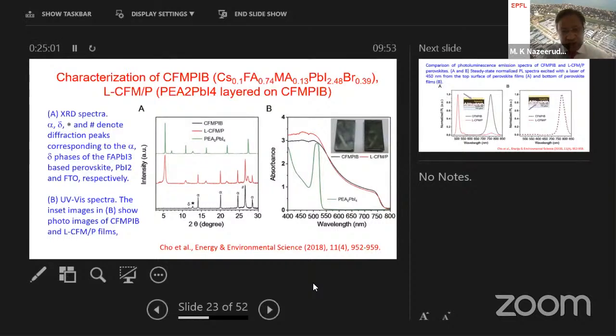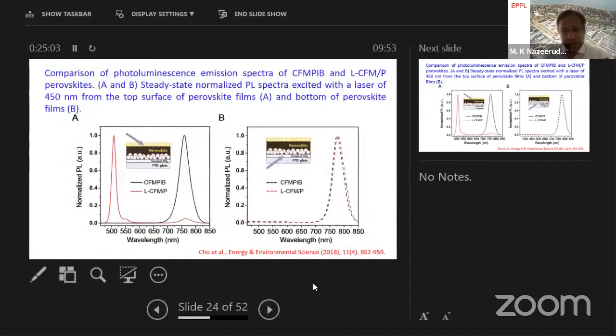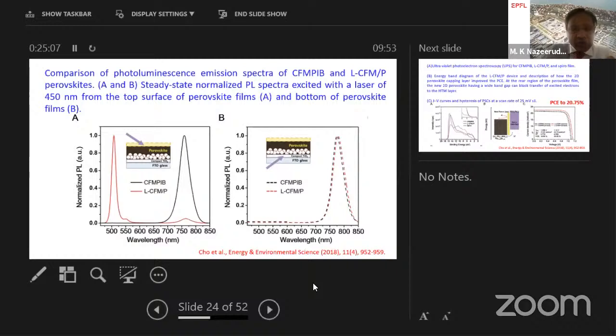Now, if we go to the luminescence properties, can you just go to the next slide, please? Since we are depositing the two-dimensional perovskite on the top, you should be able to see whether this perovskite layer is there or not. By exciting at 450 nanometers from the top side, the corresponding emission spectrum is the red line. Now, if you look at the reference sample, that's the black line, excited at the same wavelength, the black emission line comes around 780 nanometers. That's due to the pure three-dimensional perovskite. So this is another evidence to demonstrate that the layered perovskite is deposited on top of three-dimensional perovskite.